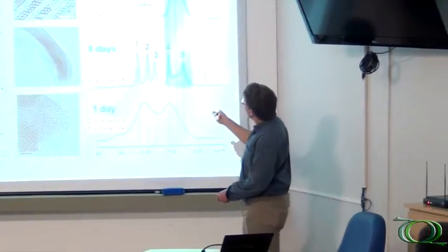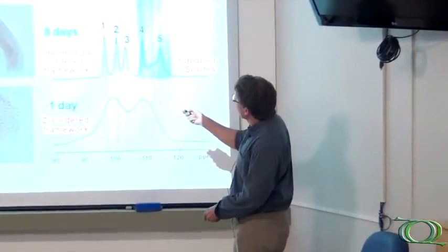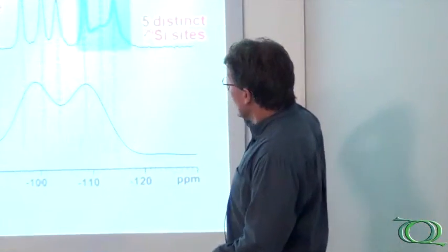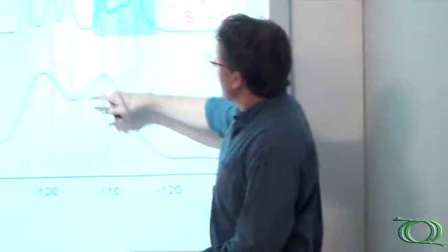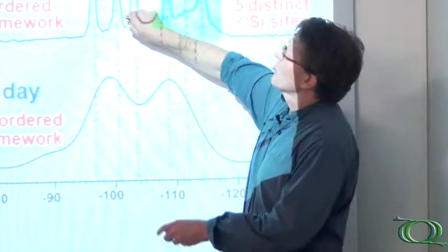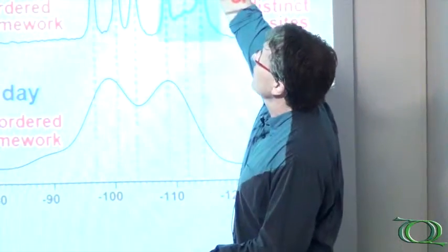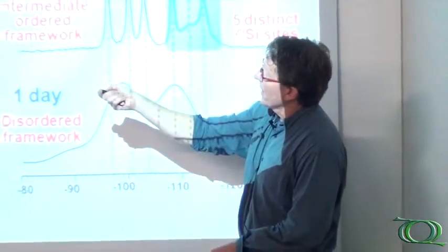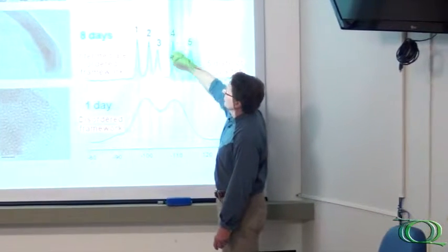These Q3 sites out here are the ones that are on the surface. So what's happening is this is going from a disordered framework to a layered structure onto a zeolite material that we can use X-ray to establish and the NMR we'll come back to.